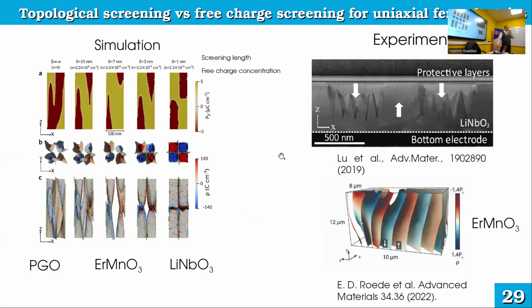We decided to make a full theory for all the uniaxial ferroelectrics, because I already mentioned that in lithium niobate you have charged domain walls. And for example, in erbium manganate, you have charged domain walls, but with some saddles. But now the structure is disconnected, so it's not a singly connected surface. And we introduced, again, free charge carriers inside the volume of material. Depending on the concentration of free charge carriers, we get a non-charged domain wall that is singly connected all over the volume of material. Then a domain wall with low charges, but with some disturbance, with some tears. And finally, we get very strongly charged domain walls for a large concentration of free charge carriers, which is actually a non-singly connected surface.